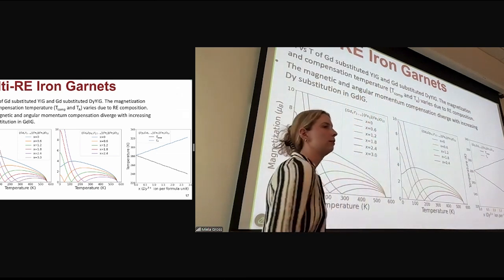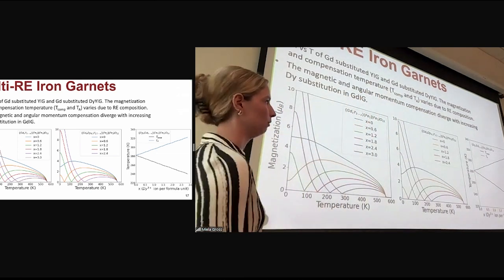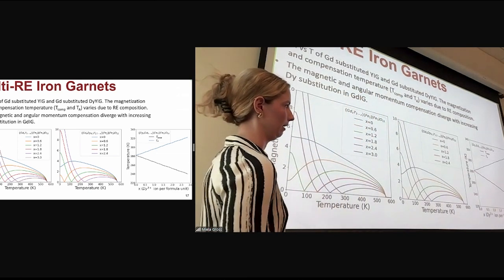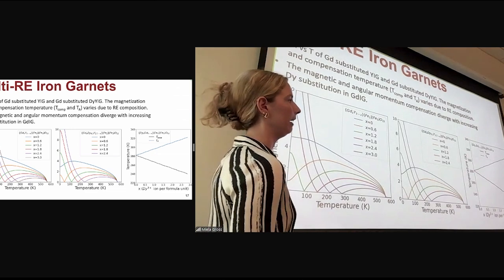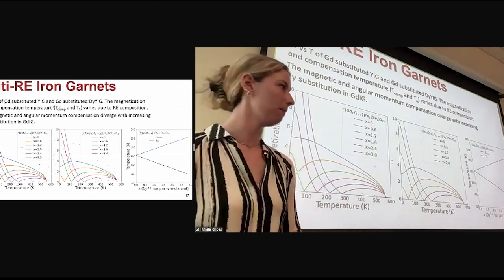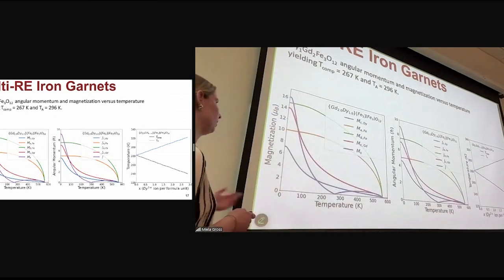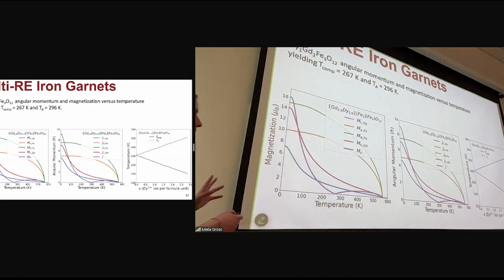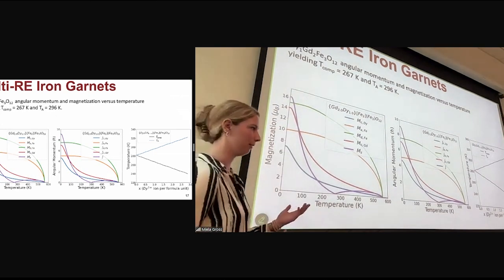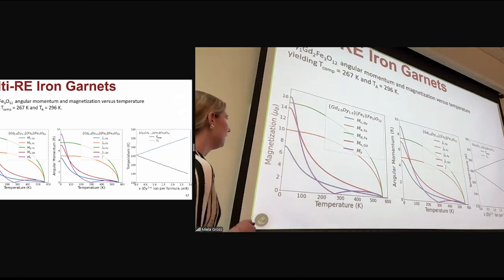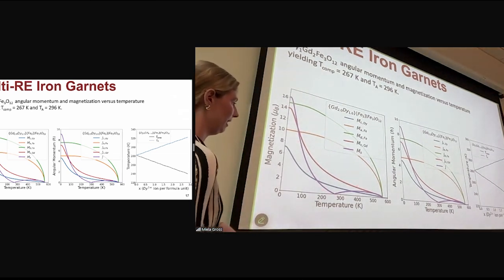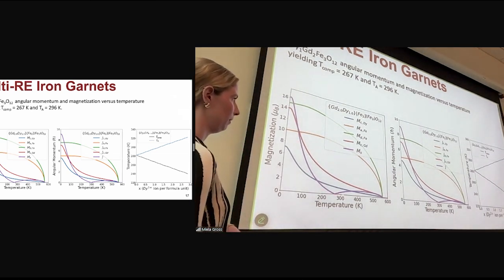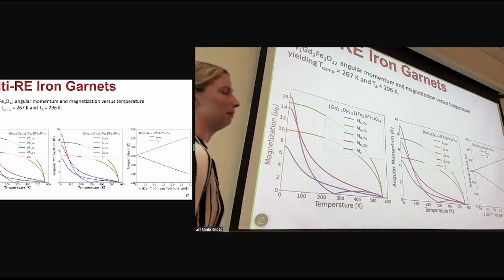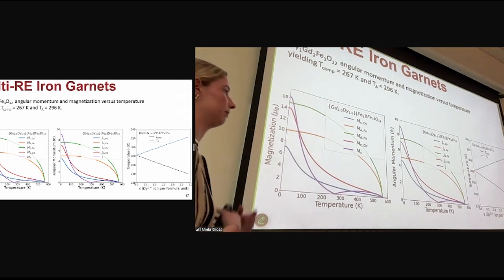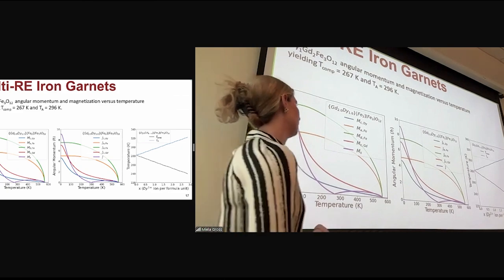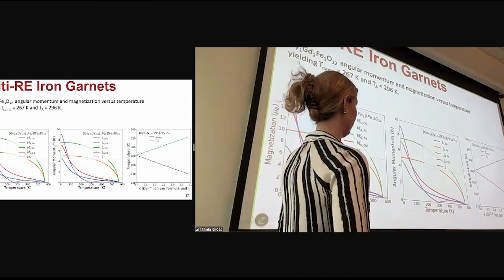So this might be useful for a researcher who wants to model dysprosium gadolinium iron garnet with a TA near room temperature, for example. So that model would tell you, okay, you want to have gadolinium 2, dysprosium 1 iron garnet to get that kind of composition. And you can see that this model will not only plot the net magnetic moment as a function of temperature, but also what each sublattice does to help the researcher visualize. And then on top of that, it'll plot the same thing, but for angular momentum as well.